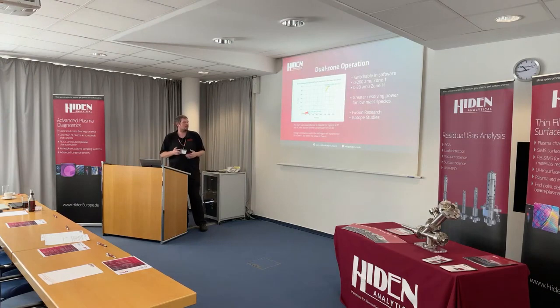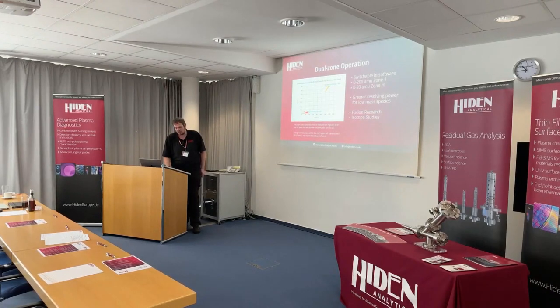So linked in with the EQP20 is the dual zone operation. All of our other quadrupoles run in what we call zone 1. This is a stability diagram. Normally, when you're sweeping the mass, you're increasing the RF and DC volts and hopefully just skimming the top of these stability regions. But there is another stability region, which we call zone H, which is at much higher RF and DC volts.